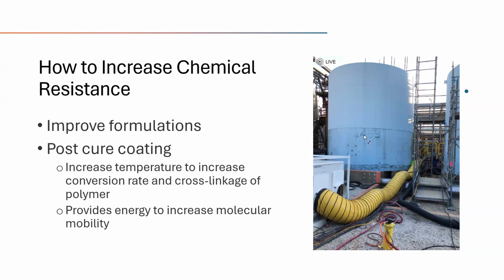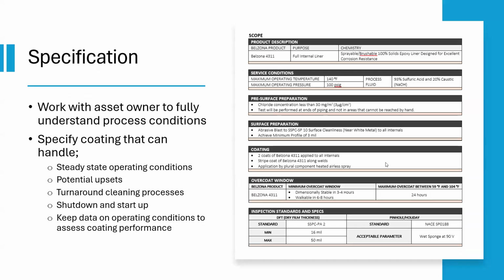If you're looking at this picture right here, we have our AC and heating duct into this tank. This tank was lined with an acid resistant coating, and we specified a post cure. So we got the tank to about 150, 170 F after the application to post cure it and get more cross linkage within the coating. So you can do all the right things, create the best product, but if you don't specify it correctly, it's not going to work. So you definitely want to work with us, and we work with our clients to make sure we fully understand the process.